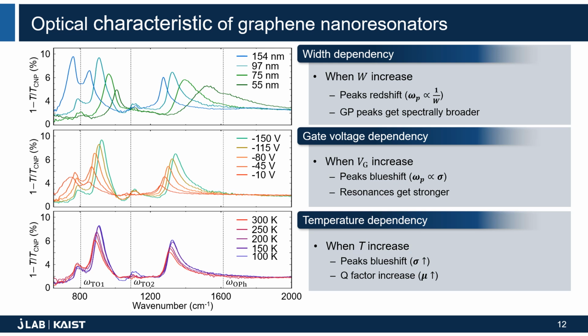SPP peak intensity tends to increase with increasing doping level unless the resonance frequency approaches the loss line. Unlike the SPP profile, GP resonance becomes spectrally broader as the resonator gets narrower. It is likely due to fabrication imperfections such as edge roughness or resonator width variation within the array.